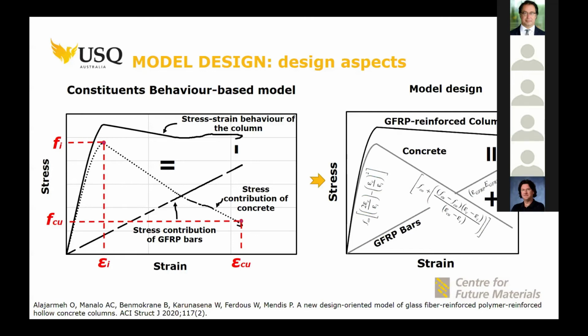There is a published paper actually out of that. So let's say in terms of strength, you can get the same strength as the tensile one if you did the test correctly. The other part is the strain is a little bit lower because the compression is different from tensile, in terms of the stress transformation inside.